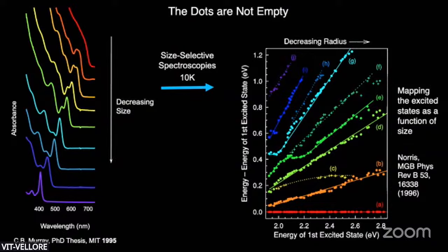What you see is these harmonics getting closer together as the size gets bigger. But something happens at one point. These harmonics start to deviate from coming together monotonically. And in spectroscopy, we call that an avoided crossing. The energy wants to cross, but it can't. That's a very fundamental quantum mechanical signature of something. In this case, it's a signature of the fact that one electron in that box is beginning to see all the atoms that exist in the box. It's beginning to interact with these atoms.